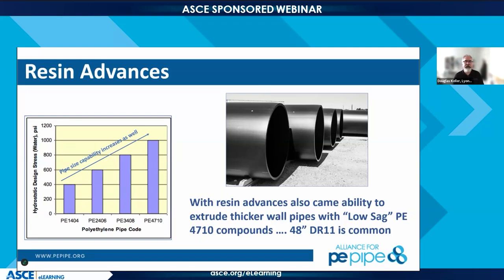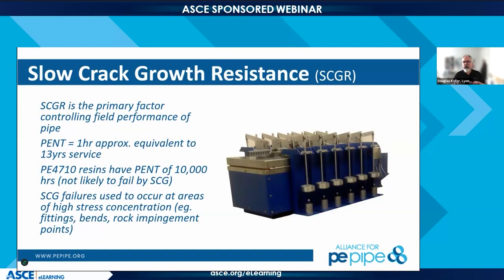3408s were the older high density polyethylenes, and now we're looking at the 4710. As we have evolved the material, we have increased its ability to handle pressure. And as Alan talked about, we have now developed a new class of materials called low sag materials, with all the benefits of PE 4710, but now we can make larger diameter pipe. So it's a great material, but it does fail. It fails long out in time, and it fails by what's called slow crack growth, or a lack of resistance to slow crack growth.